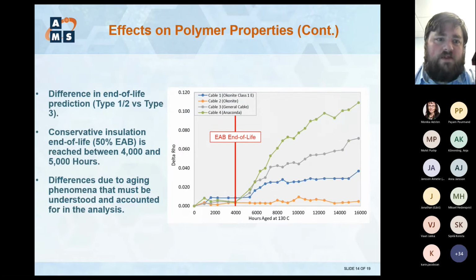So what are the implications on electrical data? So we've got our type 1s and type 2s. We've got two tests that show different things. So obviously, the type 3s are going to be affected by DLO. They're going to be affected by these different aging phenomena. So what if we were to do EAB and we said, okay, this material, this EPR right here fails at 4,000 hours, we'll say 50% EAB is a conservative end of life condition. That's just for an example in this case. But we don't see any changes in electrical data.